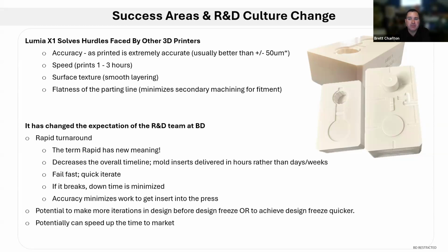We have also attempted to use our DLP printers by leveraging a handful of our high heat deflection materials, but we ultimately ran into issues. Those issues included trouble with the thick cross-section starving or just not forming during the print process, or warpage or distortion of the thick cross-sections from the print process, or if we managed to actually print the tooling successfully, the materials were overly brittle for the injection molding process, leading to immediate failure.